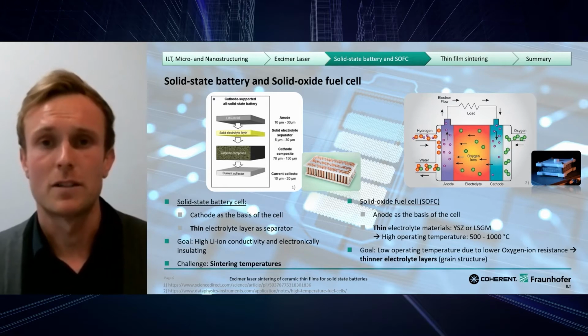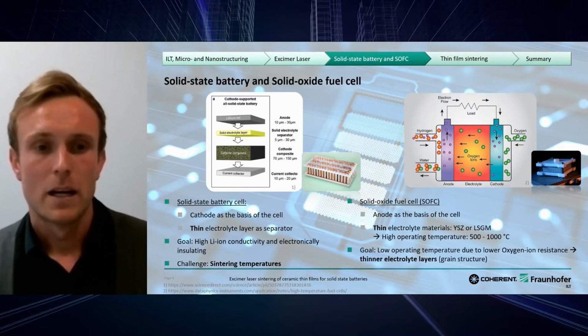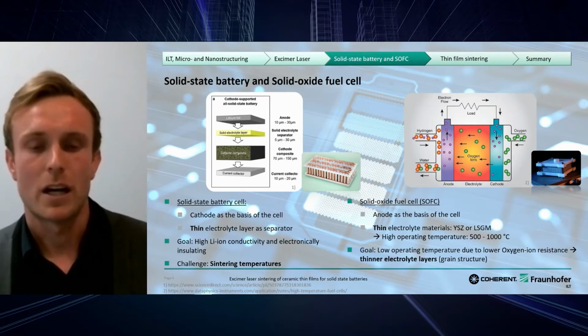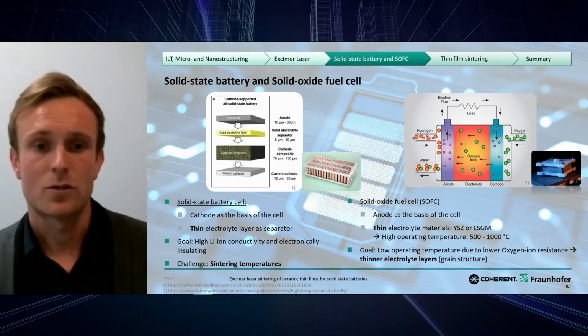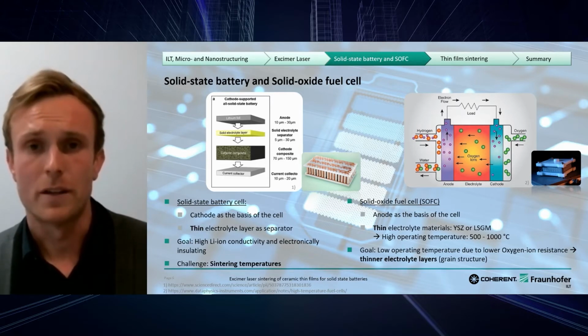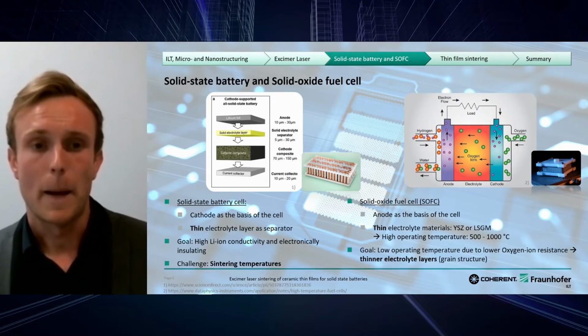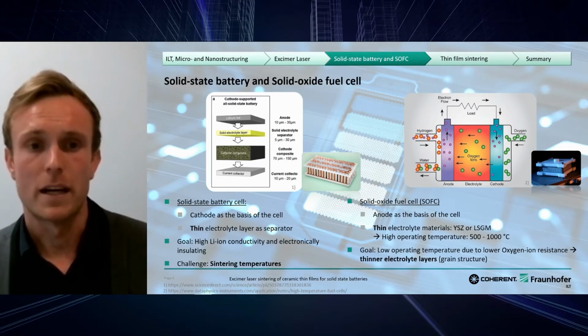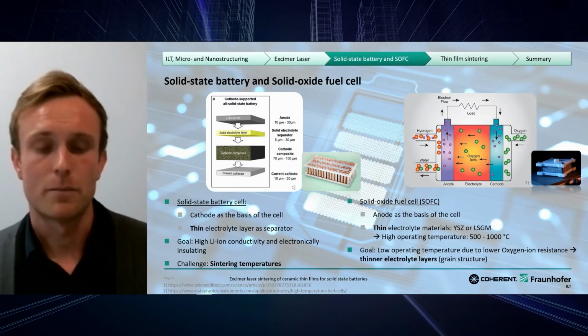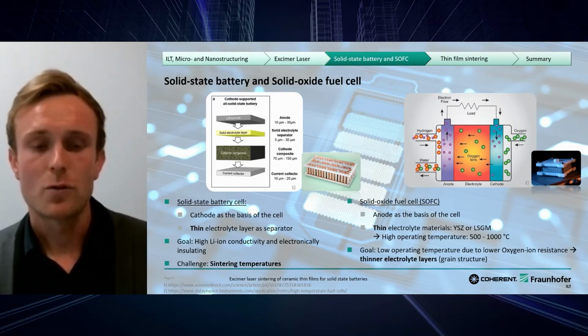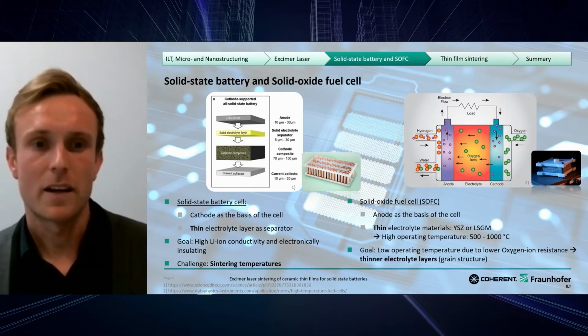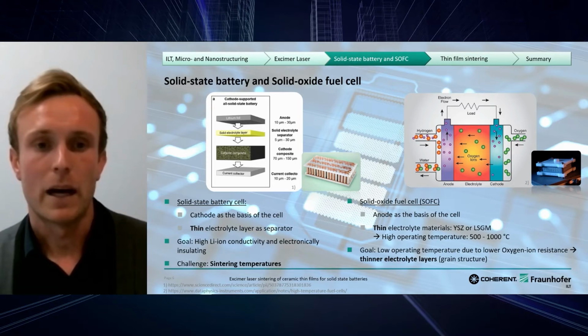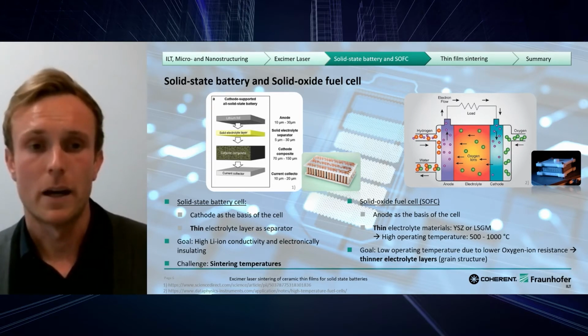And there are many requirements for this layer, but there are two main requirements. First of all, it should be highly lithium-ion conductive, but on the other hand, it should be electronically insulating. And the challenge in the production of these battery cells is the sintering temperature, because the sintering temperature of the electrolyte is higher than the melting temperature of the cathode. So we have to make sure that the energy is deposited only inside the electrolyte layer when sintering it, and we have to avoid thermal damage of the cathode.